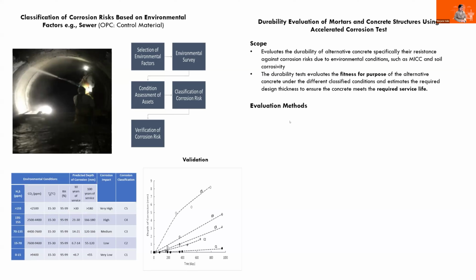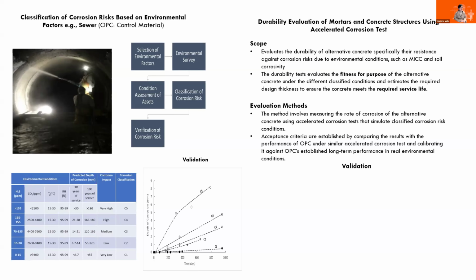So the evaluation method itself involves subjecting the materials to a series of accelerated corrosion tests that mimic the classification risk conditions. And then the acceptance criteria for the material is established by comparing the corrosion results for that material against the performance of OPC under a similar accelerated corrosion test, and then calibrating that against the OPC's established long-term performance in the same real environmental condition. Now, because we have lots of data on the OPC that has been subjected over the years from, for example, 17 to, let's say, 80 years, we're able to use that to benchmark the behavior of alternative cementitious material compared to OPC. And we therefore use that to evaluate the acceptance of that material.